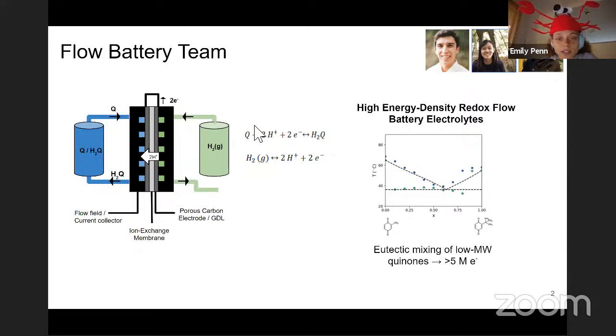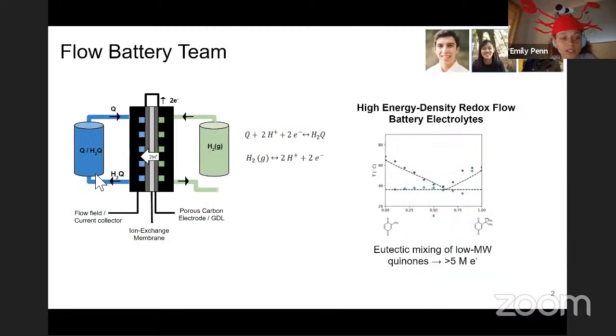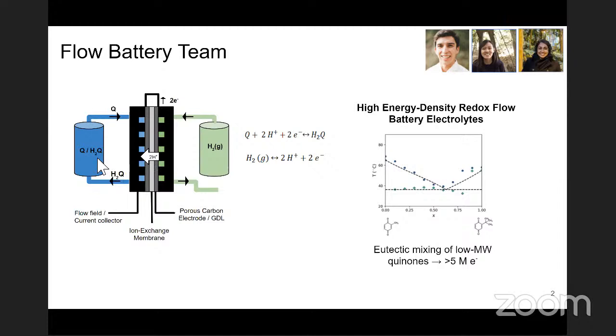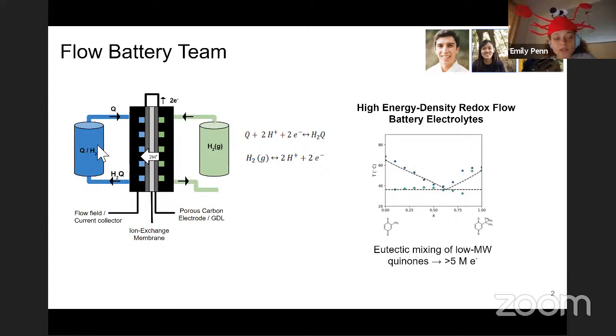So on the left here, I just have a schematic of a flow battery. Here on the left-hand side in blue, we have a quinone hydroquinone electrode. In this schematic, it's paired with hydrogen on the opposite electrode. But what's happening is we have quinones and we're forming hydroquinones as our discharge species, and that's one side of the battery. And then we can pair it with something else on the other side. In this case, it's hydrogen.